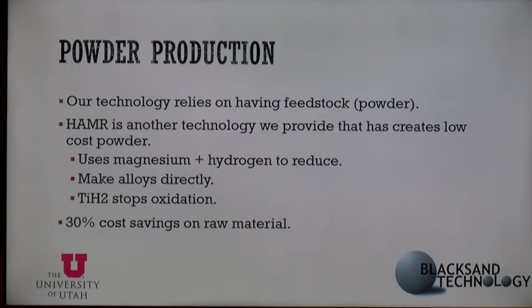So our technology relies on having a feedstock for the powder. So we need to have a powder production method that will allow us to produce parts, obviously. One of the technologies we produce is called HAMR, hydrogen-assisted magnesium reduction. Basically, it takes titanium oxide and reduces it with magnesium and hydrogen to give you pure titanium in the end.